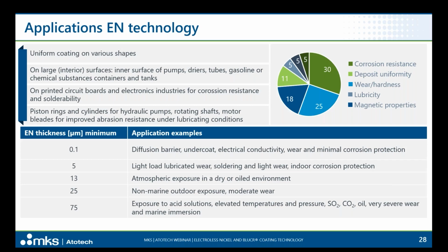And also what is good to know is that the deposit thickness plays also a major role for the application. At a very, very low thickness, we can use Electroless nickel as a diffusion barrier, as undercoat for electrical conductivity, for wear, and a bit of corrosion protection. If we increase the deposition thickness, we can use Electroless nickel, for example, in non-marine outdoor exposure with a moderate wear at 25 micrometer, and for very harsh conditions with exposure to acid solutions, sulfur dioxide, in oil and gas industry, elevated temperature and pressures, we need a higher deposition thickness, like 75, 80, 100 micrometer.